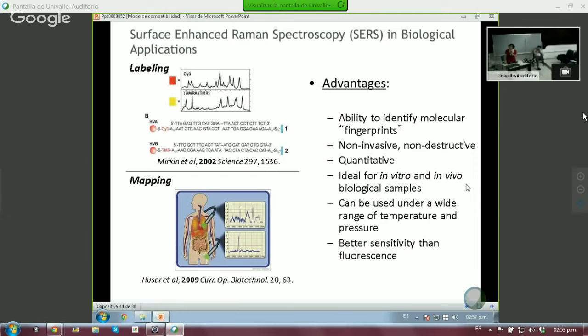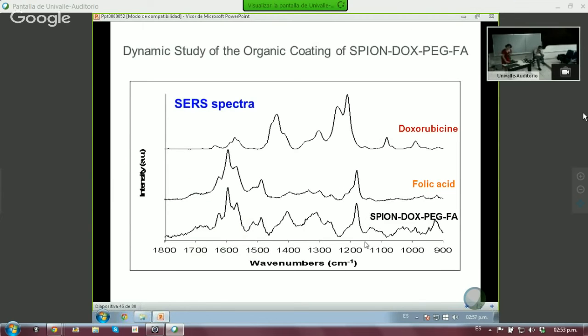And as I mentioned here, this technique is ideal for in vitro and in vivo biological samples, and it has a better sensitivity than fluorescence. Okay, so this is the SERS spectra, and what we looked at is doxorubicin. Again, this is the drug, the folic acid, and our combination of SPION, DOX, PEG, and folic acid. And what is most important for us is that you can look at it, there is absolutely nothing in the spectra which is taken from the spectrum of the doxorubicin. So in a way, this again confirms in the liquid sample that we do not have doxorubicin on the outside.